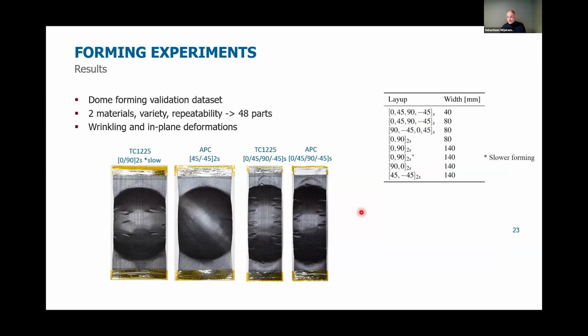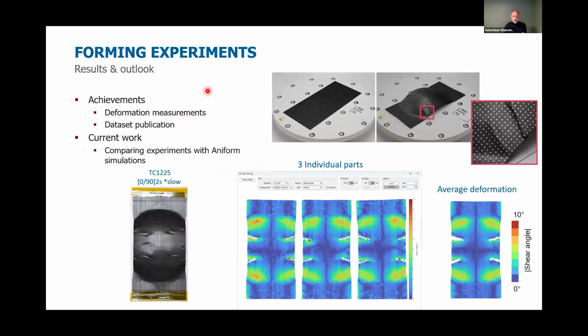Now, we've done this for quite a lot of layups here. Different widths, 2 materials, so that means 48 parts to be analyzed, looking at wrinkling and in-plane deformations. Again, the materials chosen were Toray TC1225 and Solvay APC. In terms of achievements, we are now able to very accurately measure our deformations. All the data of this set has been published. It's available, so you can have a look at all the pictures and analysis. And currently, we're comparing these experiments with AniForm simulations.